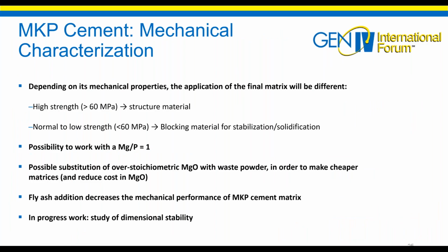In conclusion, depending on the mechanical performance, the field of application will be different. For structural materials, a strength greater than 60 MPa is expected. Formulations with lower resistance may be used in the field of stabilization and solidification. It is possible to work on the matrix by substituting excess magnesium oxide with powdered waste to create a cheaper matrix. However, the addition of fly ash reduces mechanical performance. The formulation is therefore a complex field with many parameters influencing the physico-chemical properties of cementitious materials.